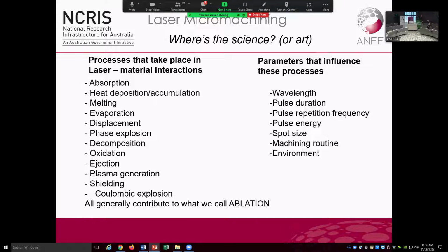To control what process dominates and takes place, you have all these different handles that you need to have a handle on with your laser. The wavelength you're using is important because it determines how the absorption proceeds, whether it's linear or non-linear or multi-photon. You also have to be concerned with the pulse repetition frequency of the laser so you don't get too many cumulative effects. Sometimes you may want cumulative effects. The pulse energy, how hard you're hitting it with each pulse, the spot size that you're getting from your laser, but then also the CNC machine you're running to get the part that you want.